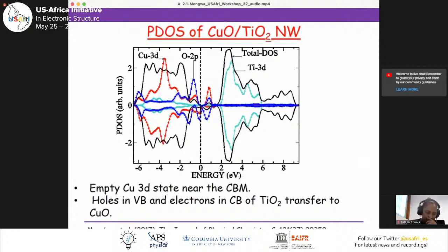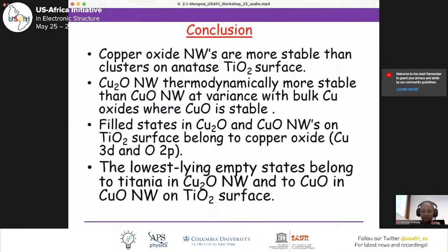We see a contrasting case in CuO on TiO2, in the sense that we have empty copper 3d states near the bottom of the conduction band minimum, and holes in the valence band and electrons in the CB of TiO2. All of them transfer to CuO. Therefore, we don't see the separation that we have just seen in Cu2O on TiO2.